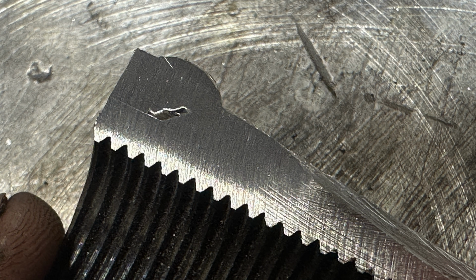I also kind of polished up the opposite side just to prove how big that cavern was, and this side's even worse. There is no doubt that over half of it didn't even fuse to the thicker thread insert, and you're talking half of 3/16. I mean, you're borderline almost 1/16 worth of fusion, depending on how much of that actually is fused. I mean, it doesn't look like there's a crack, but you get what I'm saying. I mean, that's virtually nothing.